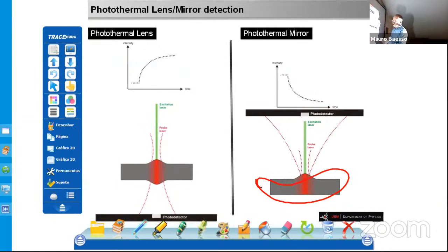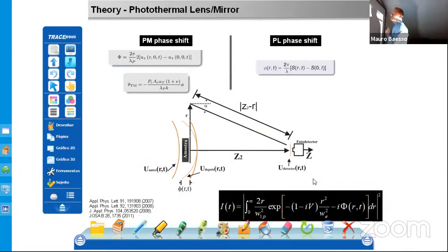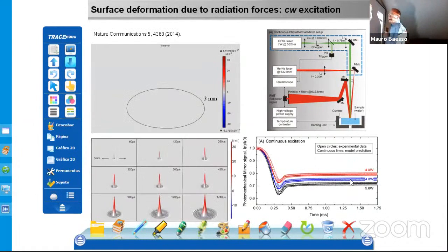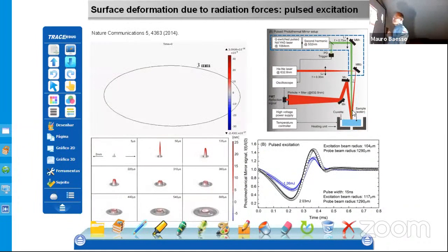It's called the thermal mirror technique. You shine the laser on the sample, you get some kind of change in the surface, and you can measure the change in surface. And just to show you, we have the model, we can calculate the intensity of the laser after reflection, and then you can get quantitative measurements. We applied that in this work in water, to observe the collision of a photon on the surface of water, and the change in the surface. We made the model, we evaluated the momentum of the photon, and just to show you that the technique is, in our view, ready to be used for imaging measurements.